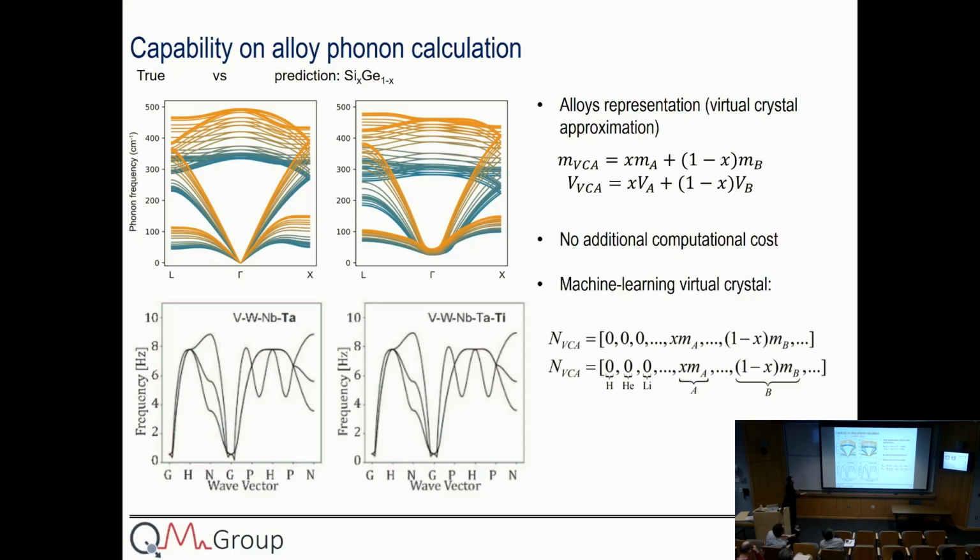In the particular case of the machine learning approach with the graph neural network, what you can do is directly put in different atoms, because the different components represent different atoms. If you turn them on simultaneously, that will represent these two atoms coexisting in one site. And on the other hand, when you put in different numbers, that is like the mass also getting weighted. By doing that, you can even directly predict some high entropy alloy phonons without doing this Brillouin zone unfolding process.